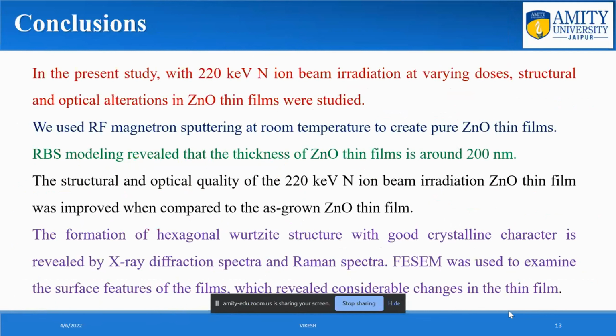Now the conclusion. In the present study with 220 keV ion beam irradiation at varying dosage, structural and optical alteration in ZnO thin film were studied. We used RF magnetron sputtering at room temperature to create pure ZnO thin film. RBS modeling revealed that the thickness of ZnO thin film is around 200 nanometer.